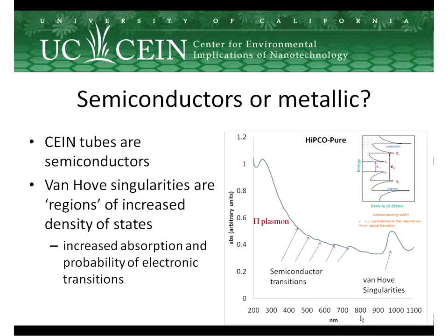So they are semiconductors, and when we look at their spectra, if we put them in the spectrophotometer, what we see is that there are a number of so-called semiconductor transitions, which means that a photon can be picked up by the carbon nanotube and it gets excited. All these different jumps from the original energy state, the valence, to the conductive energy state can generate a number of transitions.